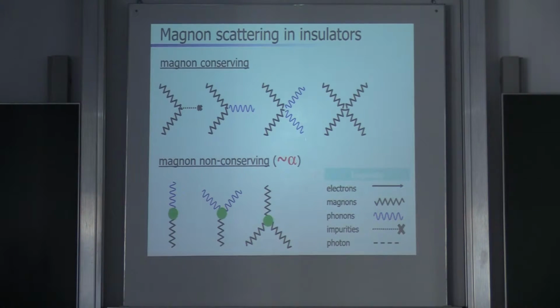Now, this one here is another scattering process, right? A magnon is not absorbed, but a magnon is scattered, and the phonon is also scattered. This, again, will be the same. It will correspond to diffusion of the magnons and also energy exchange. Now, then there is magnon scattering, which also sort of thermalizes the magnon distribution. Now, these are all magnon-conserving, spin-conserving scattering processes.